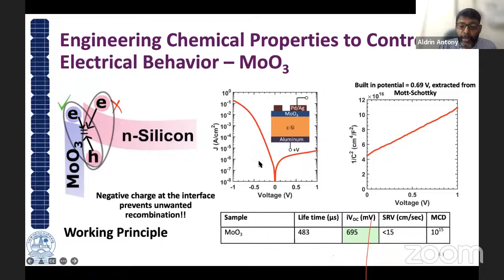And if you take a MOS capacitor, you can make this MOS capacitor using this, and then measure the built-in potential formed at the junction of MoO3 with the crystalline silicon. It was found to be 0.69, that is 0.7 volt, a built-in potential formed with MoO3. And it is almost the same as what you get with a normal crystalline silicon and N-type thermally diffused layer.